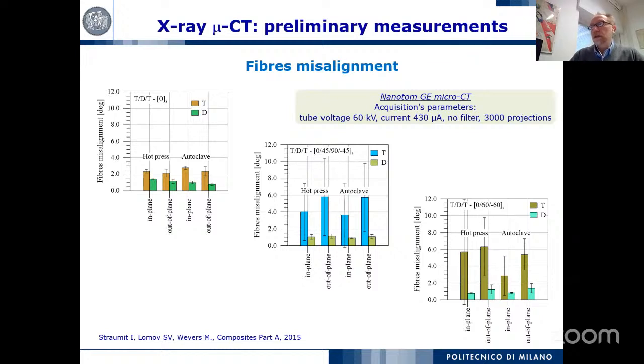For all the stacking sequences, from unidirectional to quasi-isotropic laminate, we can see that in terms of fiber misalignment, the manufacturing process does not give a huge difference. Mainly, the misalignment that is not so relevant is in the high elongation ply.